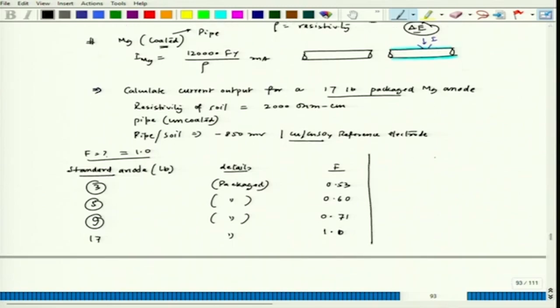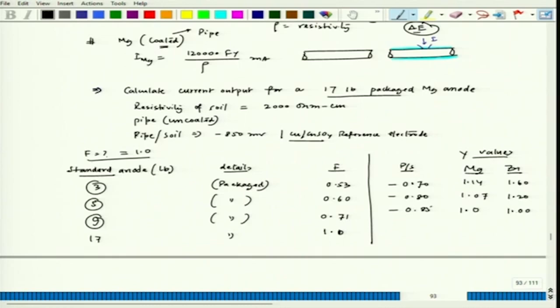On the other hand, you can also find Y from the table. Here P by S, which is the pipe to soil reference potential difference, if it is minus 0.80, 0.85, these are in volts. Now, for magnesium, it is 1.14, then 1.07, and this becomes 1.0. For zinc, these are basically the Y values: 1.60, 1.20, and here it is also 1, fine.